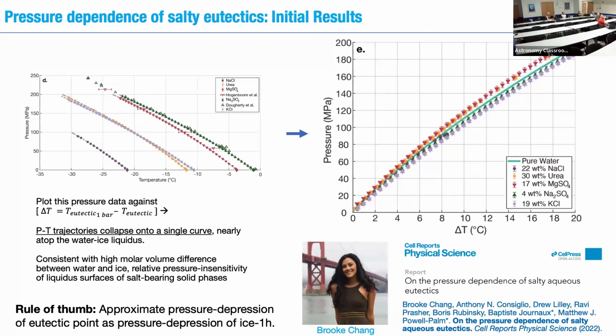The reason this makes sense to us, or I should say, when we went back to look at this a little more carefully, we decided that this should be logically consistent because the phase volume difference between water and ice 1H is huge, right? We're talking about a 9% difference, wherein the solid phase is less dense than the liquid phase. So water's weird, uniquely large volume difference means uniquely responsive to pressure. Whereas when you look at the pressure dependence of the liquidus surface of the solid solute phase, like hydrohalite in NaCl, these are relatively insensitive to pressure, right? So just because water ice has this incredible thermodynamic dependence on pressure, that's dominating the behavior of the eutectic as a whole, and the relative pressure sensitivity of the solute phase is just not contributing a lot.